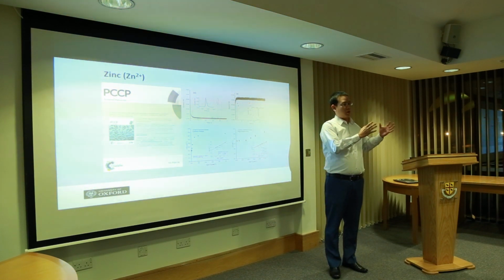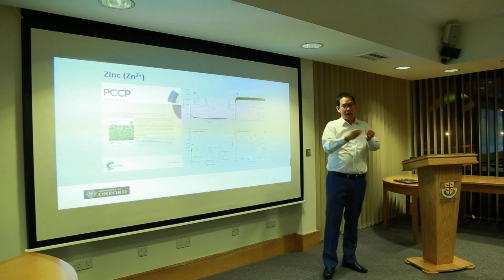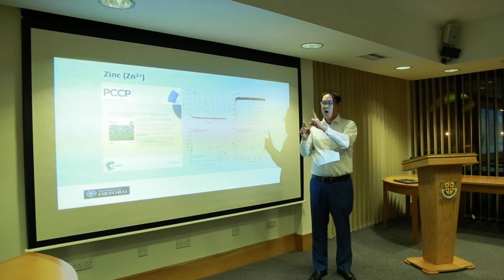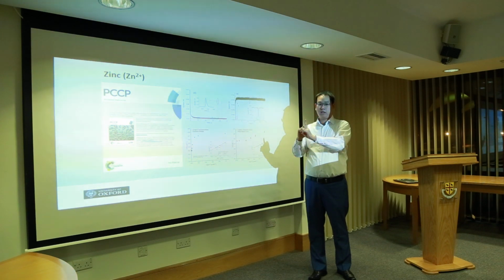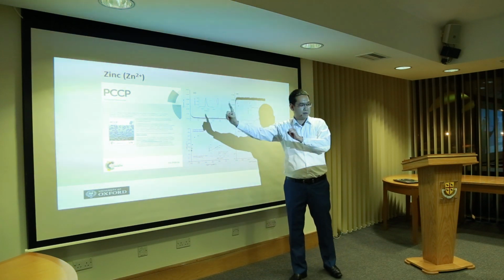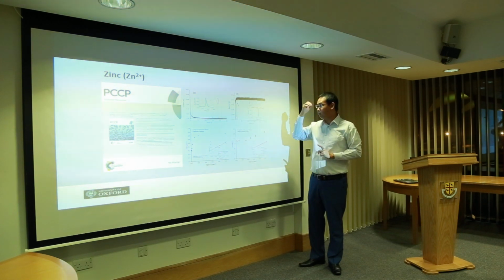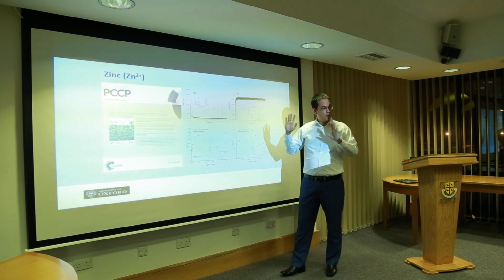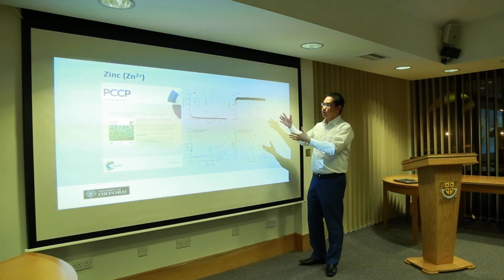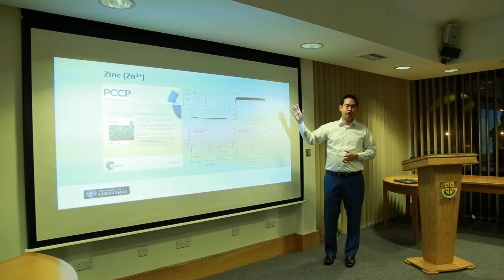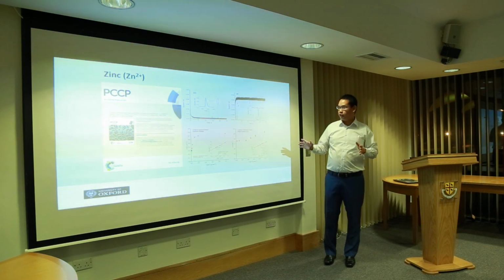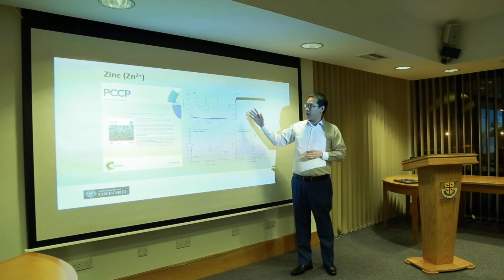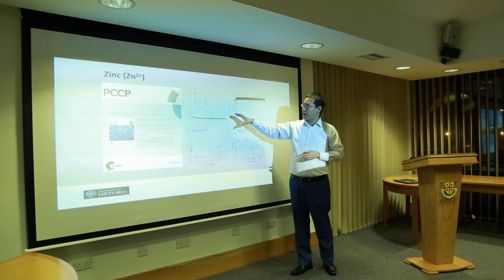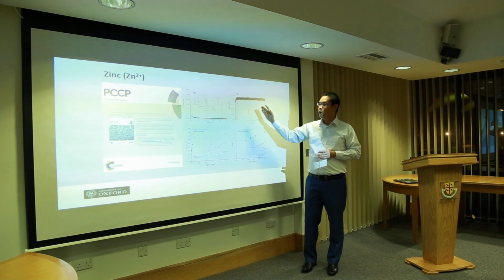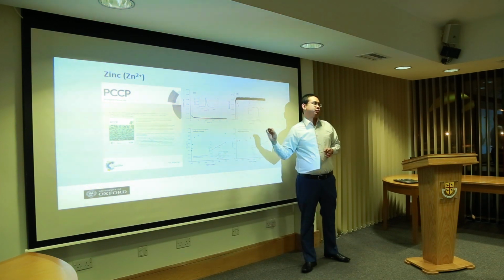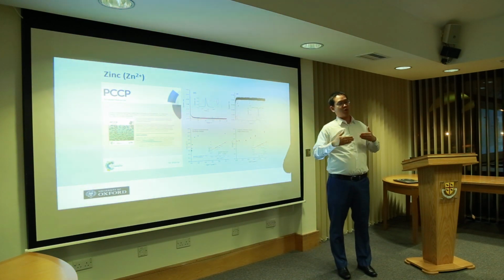The first one, we talked about bulk conditions in the macro system, and now at the single particle level, how a gold nanoparticle or silver nanoparticle can react with a single particle of zinc. And then, by applying a specific potential, again, the keyword is potential, you can find a specific concentration for zinc. And interestingly, we can also find this zinc either in an oxidation or reduction process that follows the Langmuir adsorption process. It means that the reaction is surface controlled.